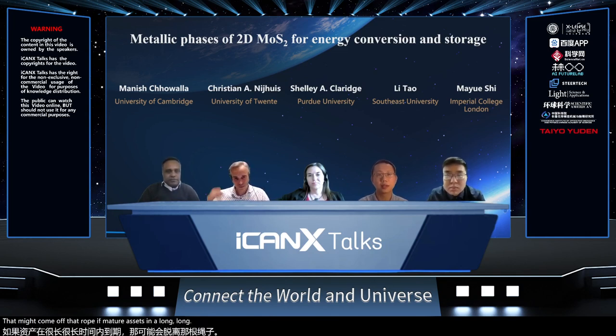So thank you. Yeah, no, that's a great question, Tao. So I think the 1T phase is metastable, and if you do anneal it to high temperature, you get relaxation.